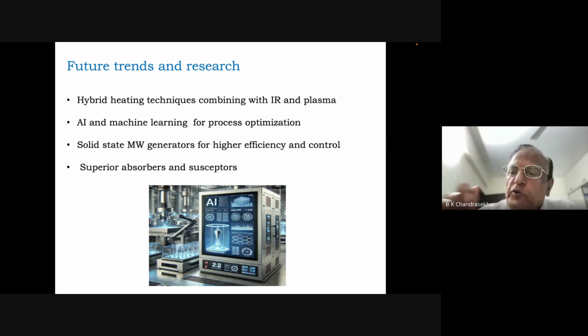So you preheat the material with a conventional method like resistance heating, and once about 600 degrees centigrade is reached, you switch that off and go in for microwave radiation. Then you can take the sample to 1400, 1500, 1800 degrees centigrade also. So this is one method of heating materials which don't absorb the microwave initially. Surprisingly, most materials at elevated temperatures become microwave absorbers, though they are not microwave absorbers at room temperature. So once you know this, this technique can be used.